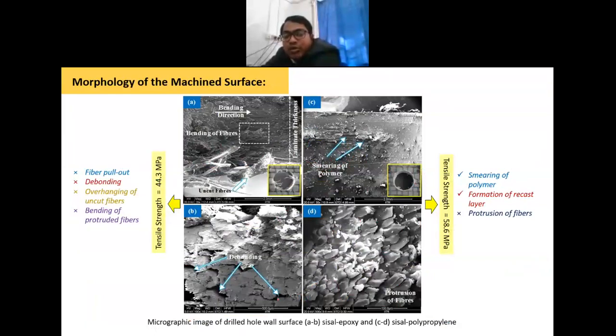And this is the morphology of the machined surface. You can see here figures A and B are for the sisal epoxy, that is a thermosetting based composite material, and C to D is a thermoplastic based composite material. You can see from these micrographic images that damage in the thermosetting composite is more as compared to the thermoplastic based composite materials. You can see lots of uncut fiber in this portion, then bending of the fiber, and also debonding, fiber matrix debonding.